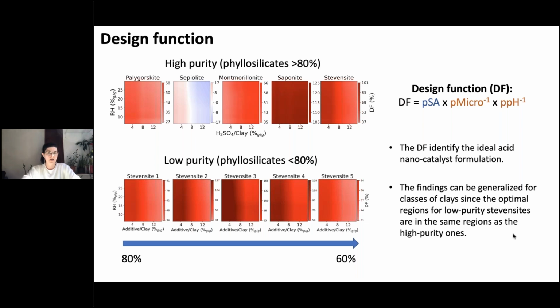5 natural minerals with high purity were explored, namely palygorskite, sepiolite, montmorillonite, saponite, and stevensite. The heat maps represent areas of improvement in red, and dark for the reduction of the design function with respect to the pristine nanomaterials. So as you can see, saponite gets improvements in a wide range of humidity and acid content, while sepiolite is effectively modified up to 5%. The optimum for palygorskite can be extended to 8%, finding the optimal preparation for this material.